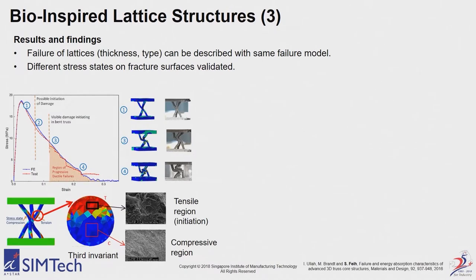So let's try. So my student had to go, because of the size, I think I made him do these tests about 10 times and he wasn't happy. But the problem was to actually measure the strains accurately during the compression testing. And when he finally got the agreement, of course, he was very happy. And the main problem there was, as I said, the resolution of the strain measurement equipment compared to the simulation. So initially, our stiffnesses weren't the same.